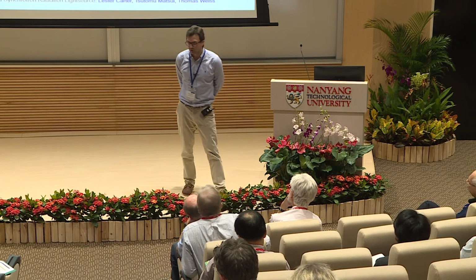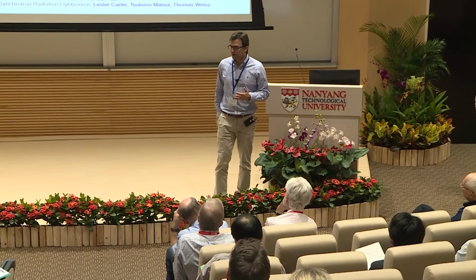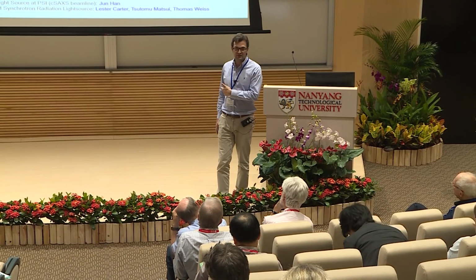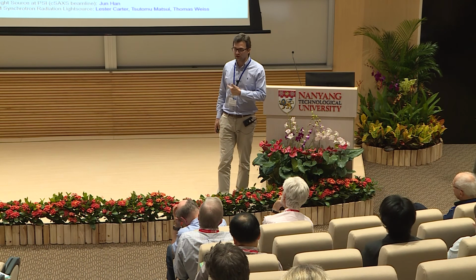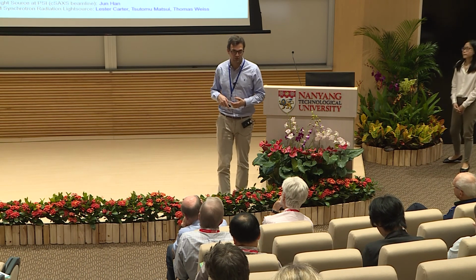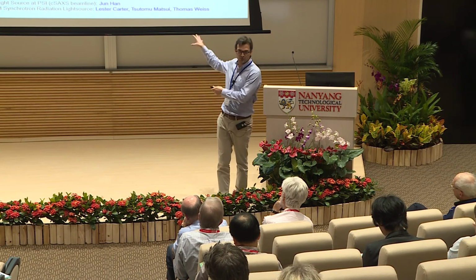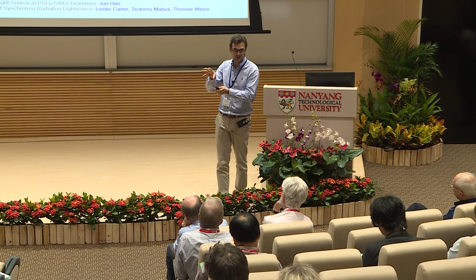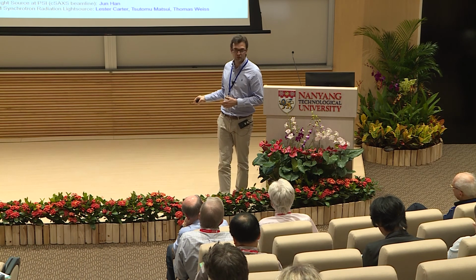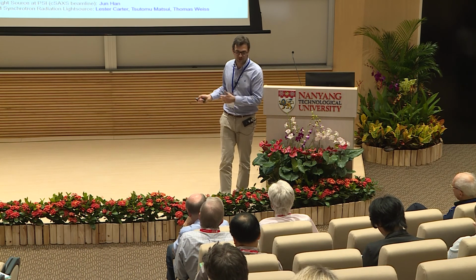So that's a good question. So, two points. Of course, the conditions are different from the ones you describe. But we did some measurements, and the integrity of our particles seemed to last for some time when we incubate them with serum. Maybe some part of them are destroyed. That I cannot say, because in SAXS you're looking at big volumes. But we seem to have the same structure when we incubate them with serum, at least with X-rays.